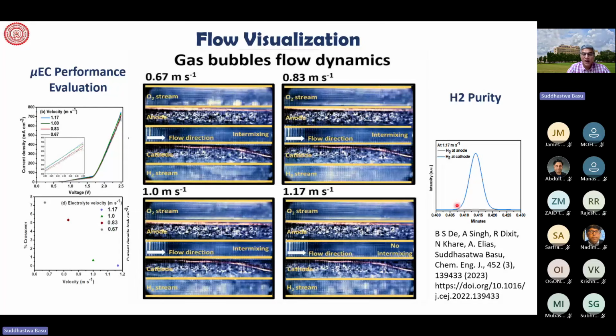So we have tested the purity of the product, whether there is intermixing taking place. No intermixing is taking place. You can see hydrogen at the anode, almost a negligible peak, and hydrogen at the cathode, because the cathode is supposed to produce hydrogen and the anode is supposed to produce oxygen. But we are testing hydrogen both at the cathode and anode. We have got a very big peak, a lot of hydrogen produced, and almost no peak of hydrogen at the anode, which shows there is no intermixing.